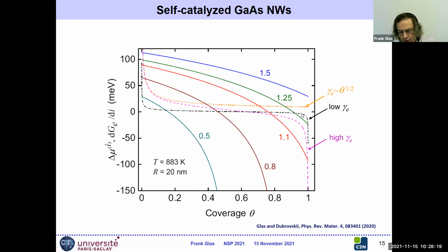The black one is for a fairly low step energy, and the violet one is for a larger step energy. What we want to see is the intersection of these curves, which again are the curves of the derivative of the step energy, with the other ones, the full curves that describe the variation of the chemical potential as coverage increases, as the droplet gets more and more depleted during this stage one. Each curve corresponds to a certain content of arsenic in terms of monolayers at nucleation. So we go from low contents, half a monolayer, to large content, 1.5.